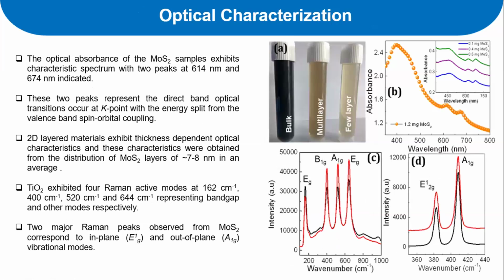Once we have that, we want to go for the optical absorption studies. Figure B shows the optical absorption spectrum obtained in the UV-visible range, from 300 nanometers to 800 nanometers. These are the optical absorptions of few layers of moly sulfide. The primary confirmation from here is the two optical absorption peaks that we have got between 600 nanometers and 700 nanometers. That's a signature peak to confirm the presence of moly sulfide.